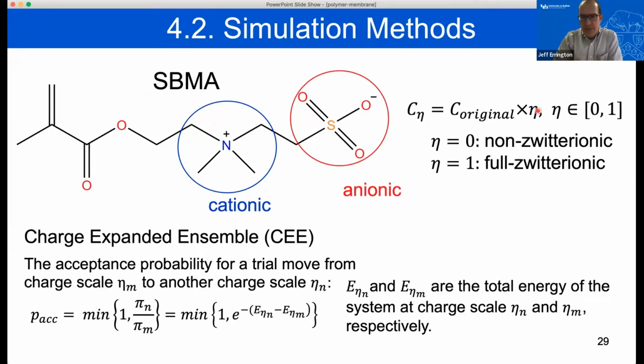I also won't get too much into this, but one of the things that we were faced when going to these systems was that these zwitterionic polymers can be difficult to sample. And so one of the things that Yichi developed was something referred to as the charge expanded ensemble. The basic idea is that you do a series of calculations where you turn the zwitterionic polymers into non-zwitterionic polymers, and you do a lot of the initial sampling with that type of approach. They sample much better than the zwitterionic ones. And then you go through this process in which you turn on the charges in various different scenarios. And in the end, it allows you to get the properties associated with the zwitterionic cases in a more efficient way.